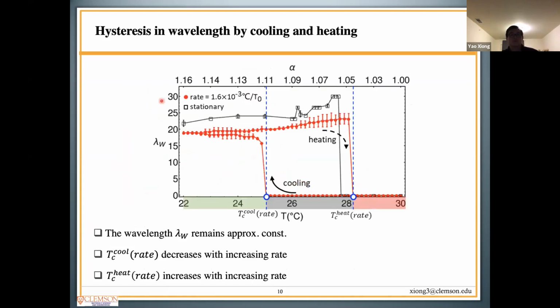By introducing cooling-heating cycles, we also observe the hysteresis loop in the wavelengths, compared with the stationary case where the confined hydrogel can fully develop the patterns at different constant temperatures. We find the dynamically controlled sample has a smaller wavelength, and the wavelength remains approximately constant during the cycles. We also find that increasing the rate results in the critical temperature during cooling being shifted to a lower value, and the critical temperature during heating would be higher. In other words, we could control the size of the hysteresis loop by changing the rate.